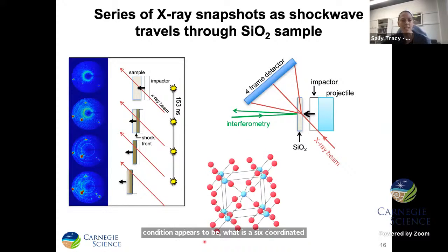However, it's really interesting in that what we saw in these experiments was that there were some important and interesting distinctions in the structure that formed, depending on whether we started with an amorphous silica glass starting material, which is typically what would be used, for example, for high power optical applications, as opposed to starting with crystalline quartz, which is the stable ambient phase or the mineral structure. We were able to show very clearly that for silica glass, we observed crystallization of a high pressure phase known as stishovite, which is the same phase that would be observed in a static compression experiment. However, when we shocked crystalline quartz, which is the mineral that one would likely find at a place like Meteor Crater, instead we observed a 6-coordinated disordered structure.